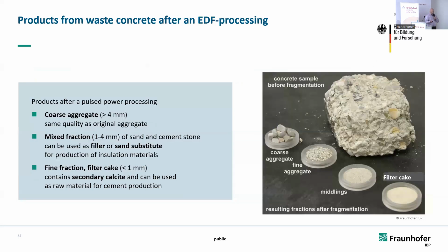we are obtaining 3 different fractions. We obtain a coarse fraction bigger than 4 millimeters, and this is now completely free of cement stone, and this has the same quality like the original aggregate. Another fraction is a mixing of sand and carbonated cement stone, and most interesting for us is the filter cake, because this contains secondary calcite and amorphous silicates.